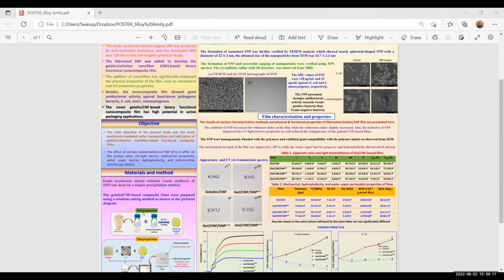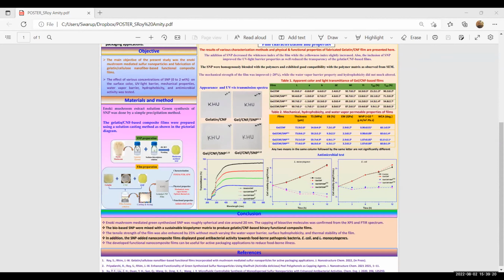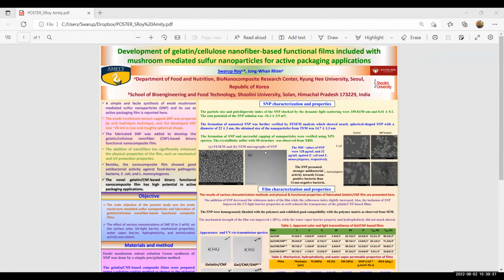So as you can see from this schematic diagram, this is the preparation method. Enoki mushroom extract is prepared, and then sodium thiosulfate is used as a source of sulfur, and dilute HCl is added to produce the mushroom-mediated sulfur nanoparticle. And it is characterized using various analytical techniques. And from SEM, we can see the size and shape of the nanoparticle. The produced nanoparticles show good antibacterial activity, as we can see from the bacterial morphology, control, and sulfur nanoparticle treated. And it is more active toward gram-positive bacterial strain, here in this case, Listeria monocytogenes, compared to gram-negative bacteria.